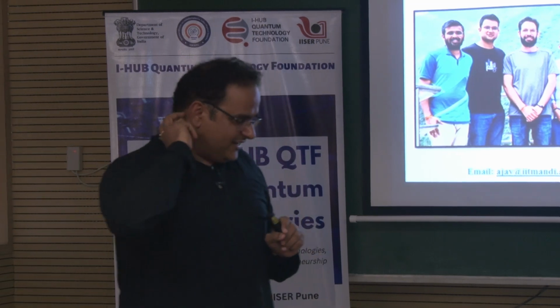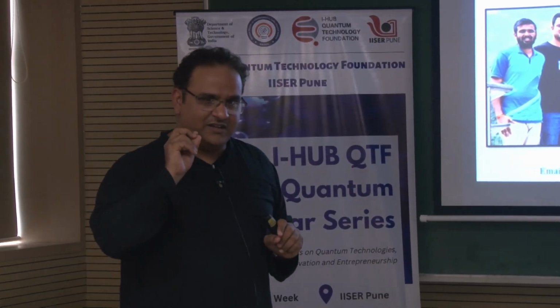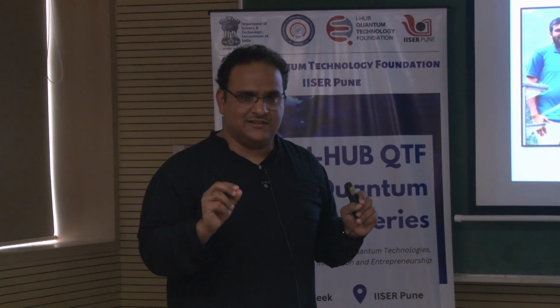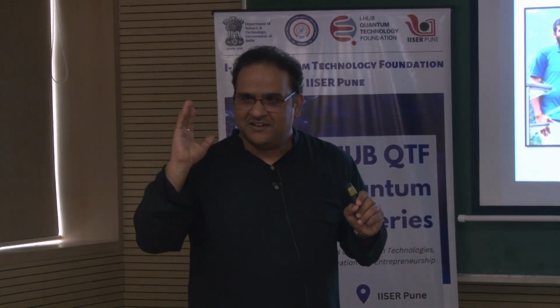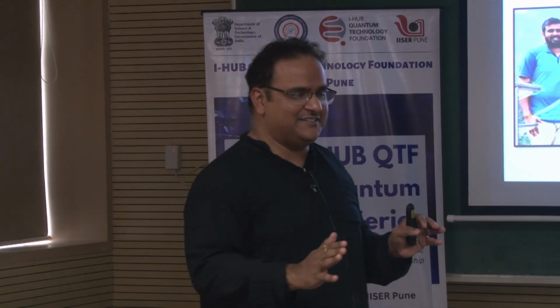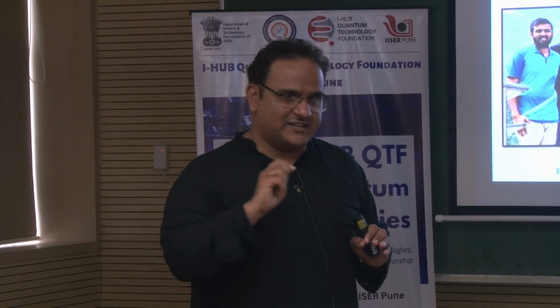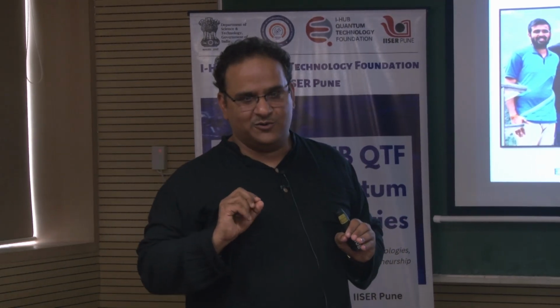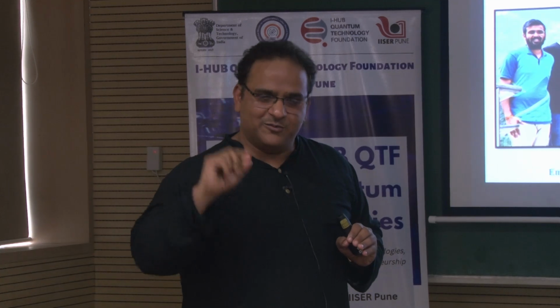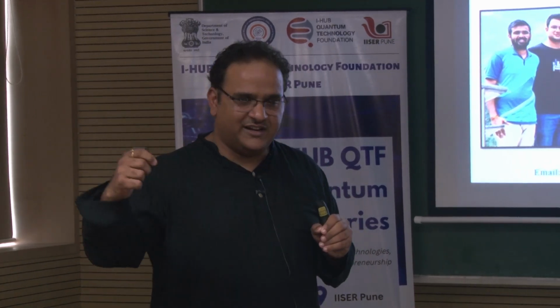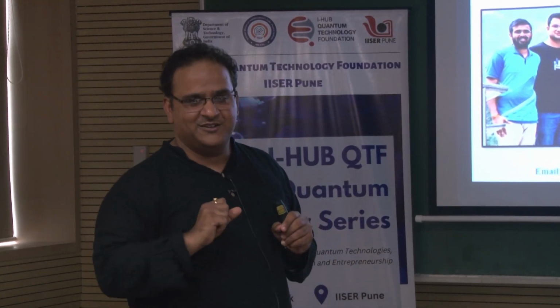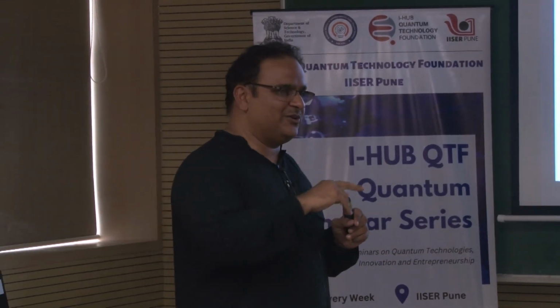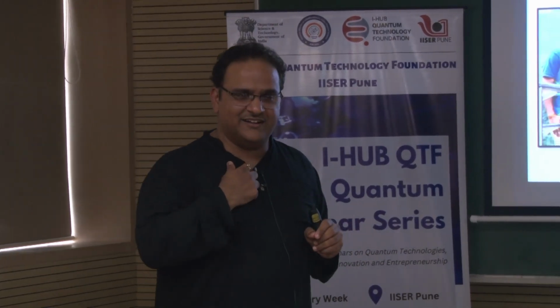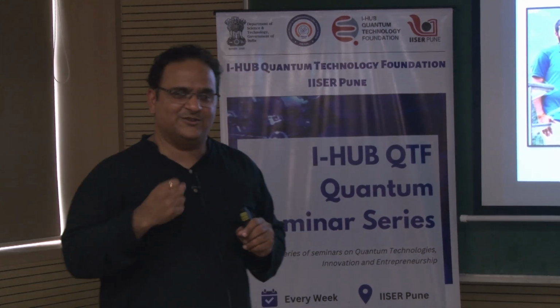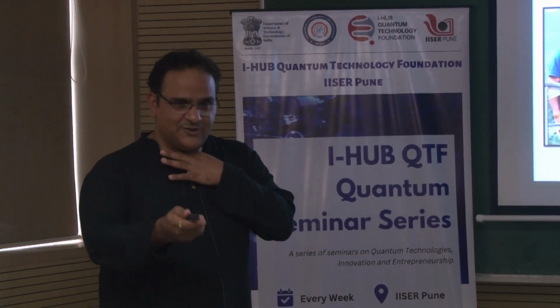Second thing, on the tantalum telluride, we are looking for some good crystal. Just half a micron is good enough for us. That's a problem because we tried in the lab, it's difficult to grow. And monolayer is even more challenging because of exfoliating, and then the substrate effect will dominate. So these are the two reasons we are not able to show it, otherwise we had this in mind as one of the good examples to show. Thank you for your suggestion, sir.